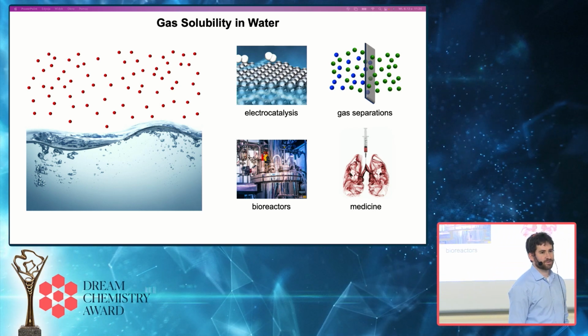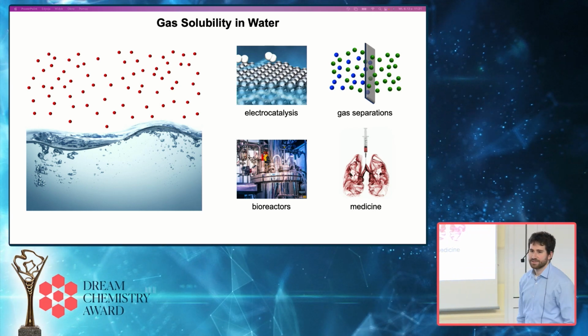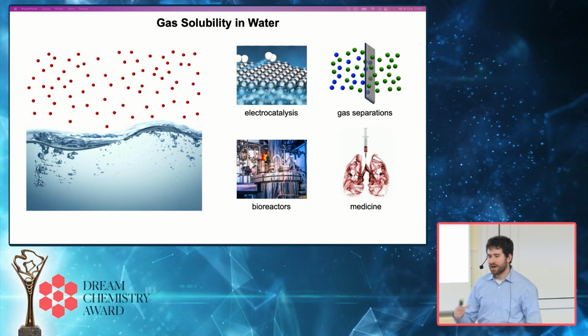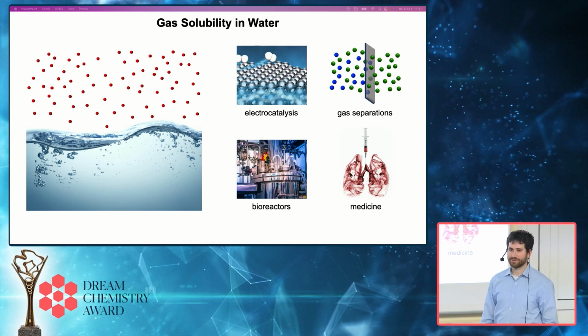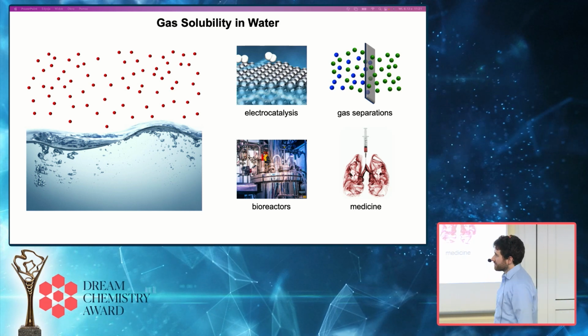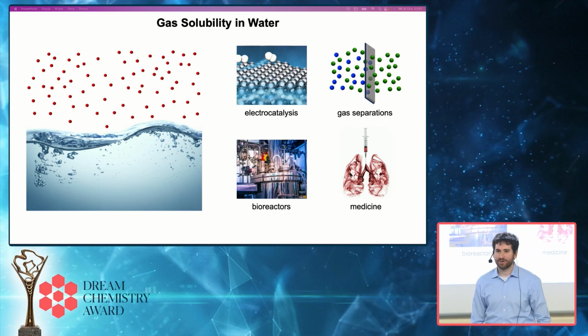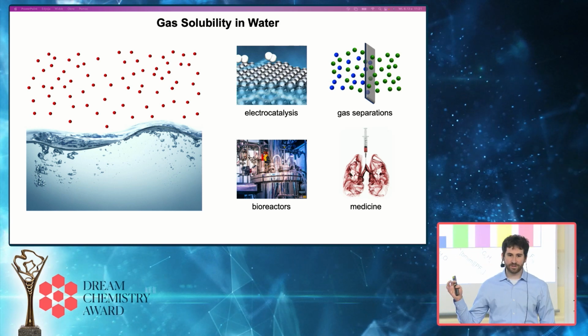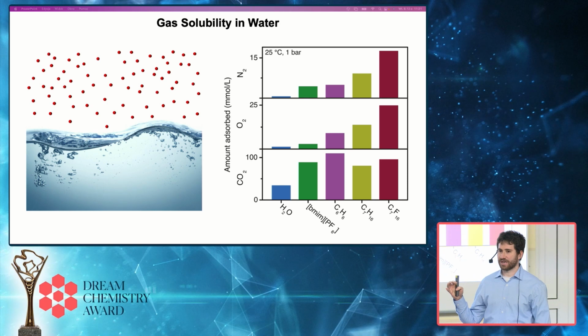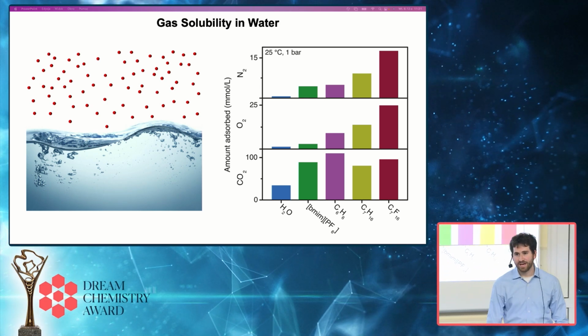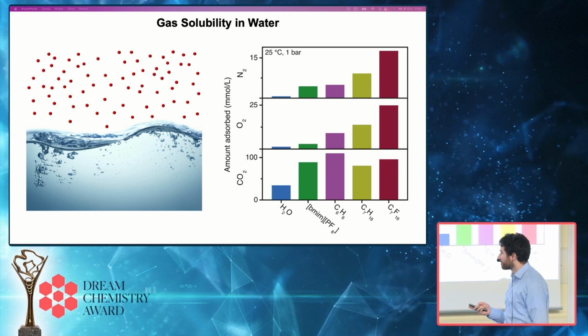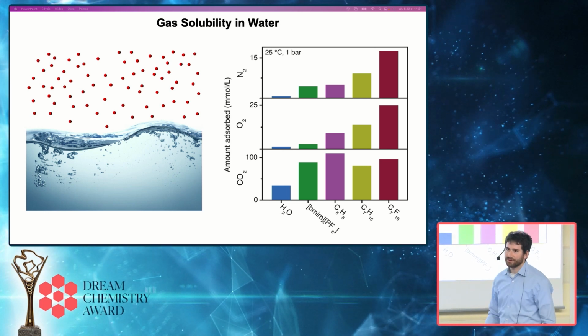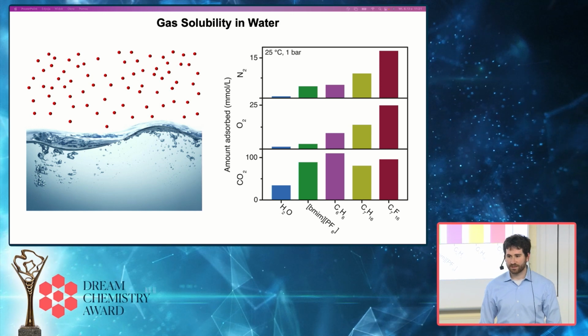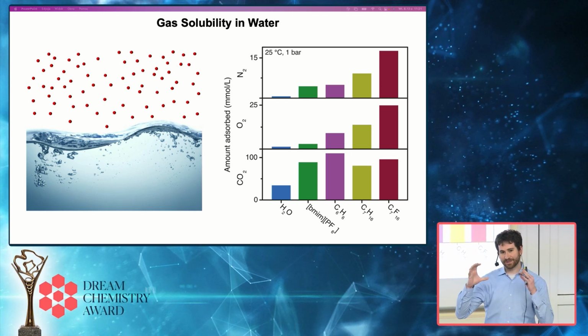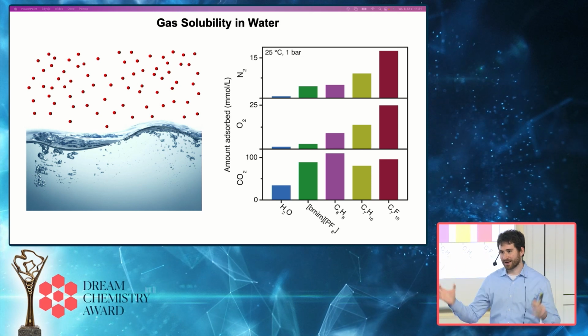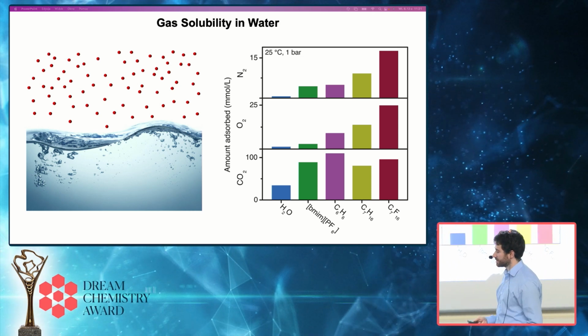And gas transport through water is, of course, relevant to a lot of biomedical challenges, situations where one wants to get oxygen either into the body or for ex vivo applications like organ preservation and some other things that we'll touch on later. The reason transporting gases through water can be quite challenging is because water is a very polar, strongly associated solvent that does not do a very good job of solubilizing gas molecules. So solubilities of most gases in water are about an order of magnitude lower than those of organic solvents or ionic liquids. Water molecules really like to interact with each other, and they don't like to move apart and to create space to accommodate gas molecules and to be able to dissolve them.